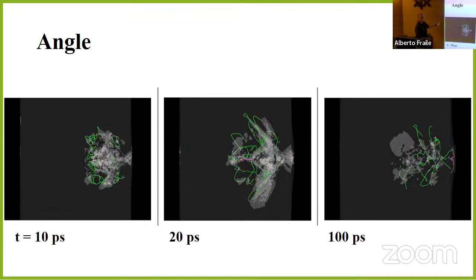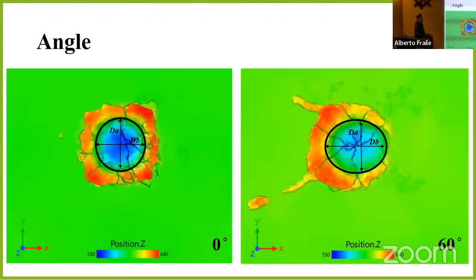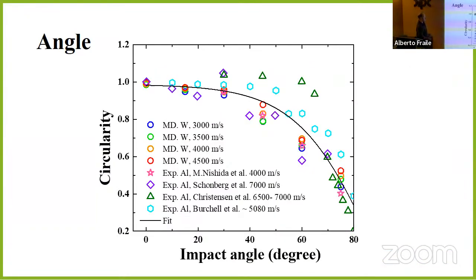This is seen from the top. So the impact was like this, and then we have these dislocations going like that, and then ending like that. And the crater in a normal impact, perpendicular, has the expected symmetry, but when we have, for example, this 60 degrees of angle, then we will have something that will be elliptical, and we can plot that. The ratio between those two axes is called circularity. So it's 1 when the impact is perpendicular, and then goes to 0 point something, and so it goes like that.